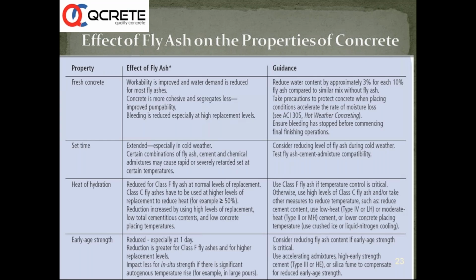So we are trying to tabulate how the properties are affected. In fresh concrete, workability is increased as the water demand is reduced. Setting time is extended. Especially, we need to be careful in winter times. Chemical admixtures may cause rapid or severely retarded set at certain temperatures. So in such cases, we have to consider either reducing the fly ash during cold weather, and also we need to be careful about which admixture we use. Heat of hydration is reduced when you are using fly ash. Class C fly ashes have to be used at higher levels of replacement, say more than 50%.